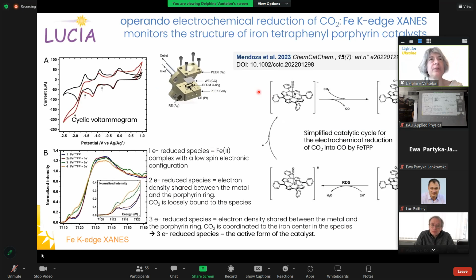And so now here a report of one of our first operando observations of reduction of CO2 with the catalyst that is iron tetraphenyl porphyrin, studied at the iron K-edge, so with a homemade electrochemical cell. And so following the iron speciation with the XANES, they could determine the modification of this FeTPP, I think they call that, during the catalysis. And also they could determine the structure that is in orange here, the reduced species, that is the active form of the catalyst during the catalysis.